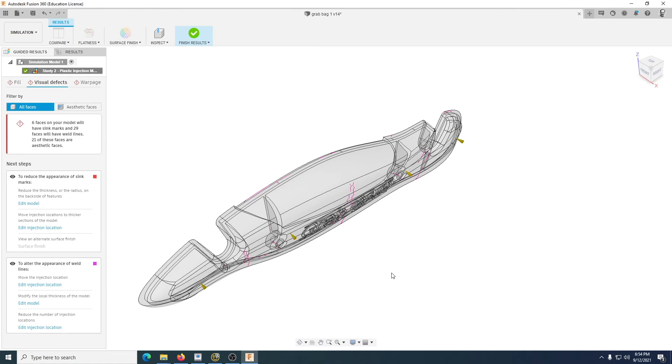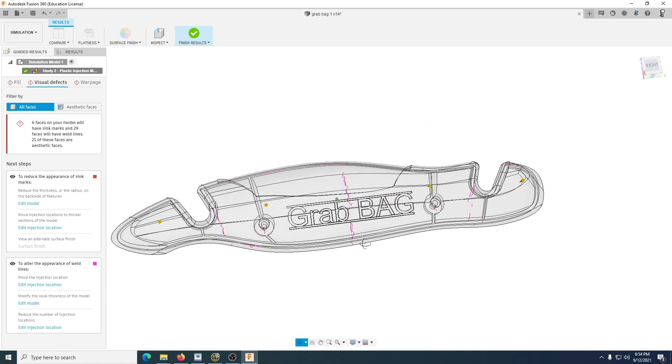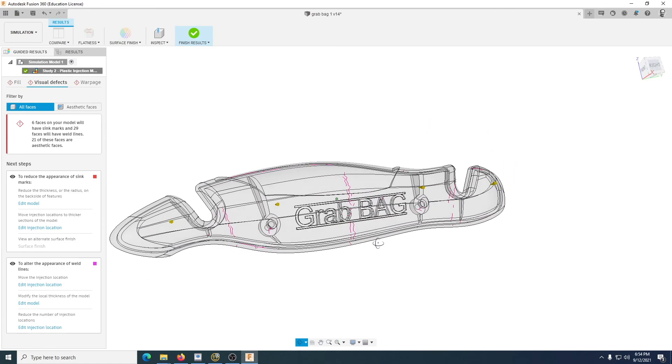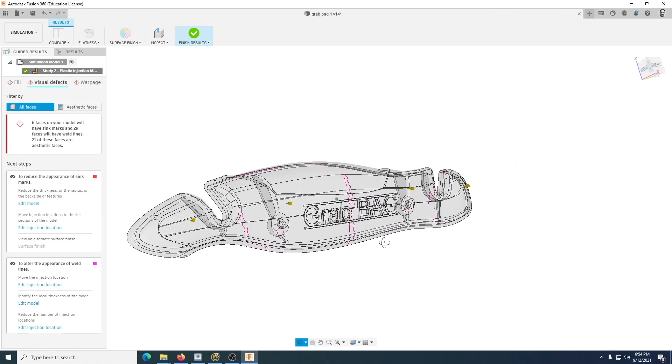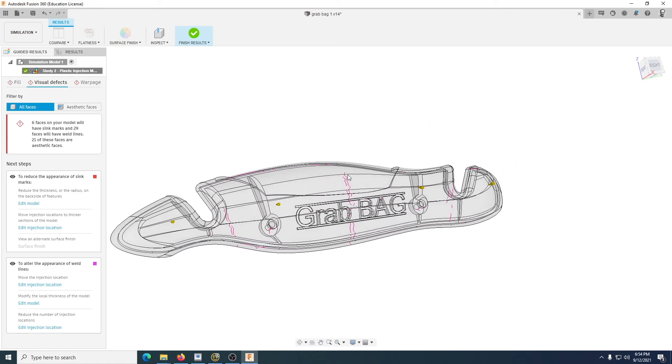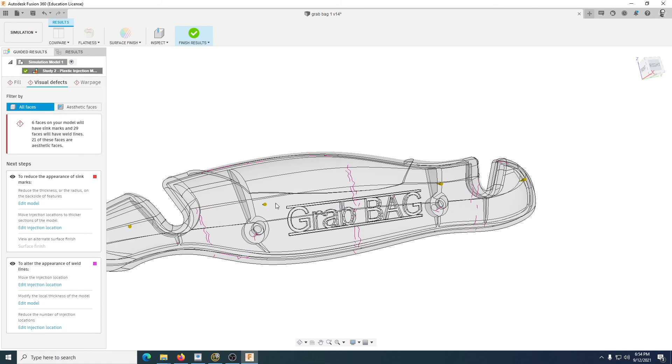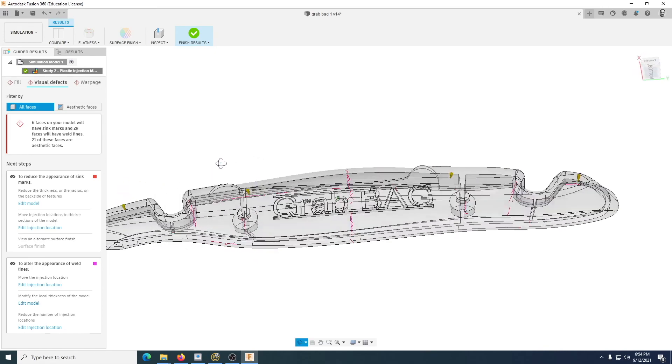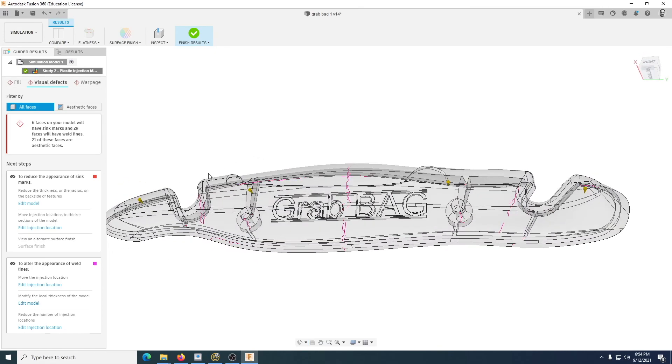We can have a look at the structural defects. You might be able to see it—you see the crack there in between the two locators? What I'm guessing is as the plastic moves there, it's cooling down. As the plastic moves there, it's cooling down and it's not really fusing properly. The further we move away from the locators, then the problem...